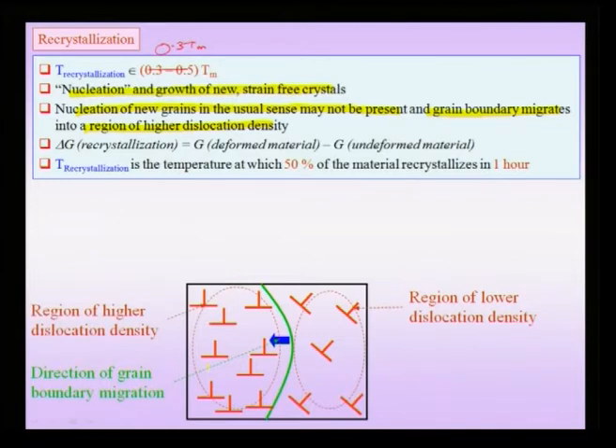So you can see in the schematic below, for instance, there is a grain boundary here, and on one side of the grain boundary there is a region of low dislocation density. On the other side of the grain boundary there is a region of higher dislocation density, and this grain boundary can sweep into this. We are assuming this is a high angle grain boundary that sweeps into the region of higher dislocation density, and in the process the dislocations are absorbed at the grain boundary, and the overall dislocation density in the left hand side crystal, or the left hand side grain, also decreases.